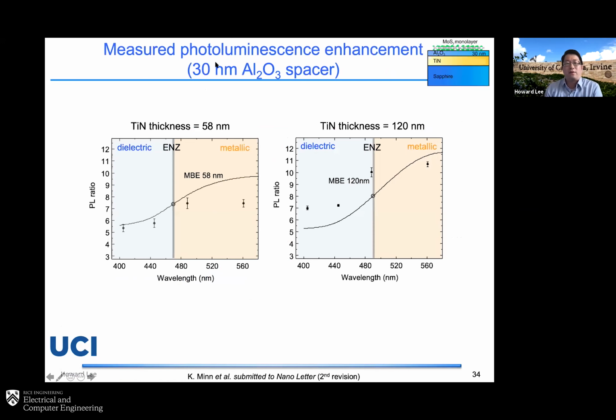So this is a result for the thick aluminum oxide spacer, 30 nanometers, and for two different titanium nitride thin films, 58 nanometers and 120 nanometers. The ENZ wavelength is here. The left-hand side is the dielectric property, and the right-hand side is the metallic property. You can clearly see that you have a transition across this ENZ wavelength from dielectric to metallic. Your PL enhancement increases when you cross this ENZ regime. And for the thicker film, you find the enhancement even stronger on the metallic side, basically because you have a stronger absorption enhancement on the monolayer.